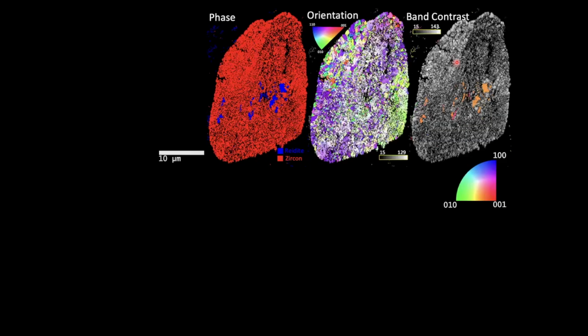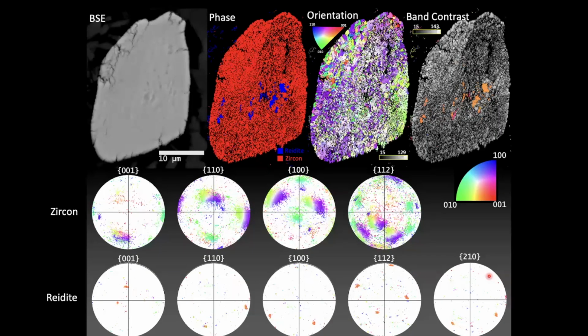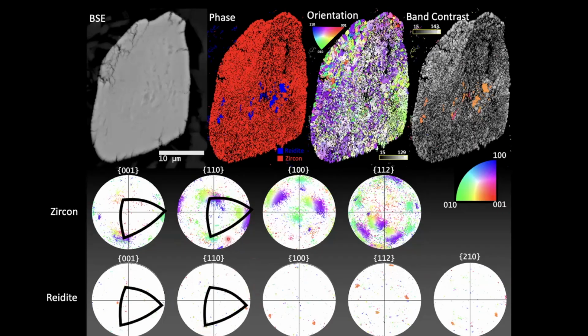So here's that band contrast, and you can see the orientations of the Reidite here, and then the backscatter. And then there are the pole figures. For this one, it's definitely harder to say for sure that there are 3 mutually orthogonal clusters. But in general, in the literature, this would be something that's clearly accepted as a systematically oriented granular zircon. What's nice is since this one has Reidite, we can actually see that relationship. You can see one cluster on the 001. You can see 2 clusters on the 110, all of which are mutually orthogonal and all of which actually overlap with the clusters for the zircon.